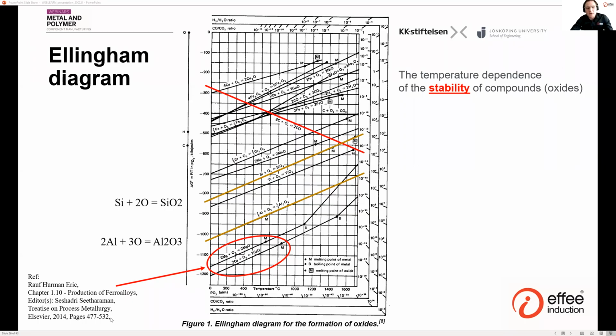This is used very much to reduce other oxides. So if you look on the right of the diagram, where this red carbon dioxide line goes down with increasing temperature, you can see that above, for example, 1400, 1500 degrees, the carbon dioxide line is lower. That is more stable than, for example, chromium oxide or manganese oxide or even silicon oxide. So then you can use carbon to reduce this, for example, chromium oxide. It's very valuable to do that when you make stainless steel, because then you can save a lot of chromium that would otherwise be in the slag and lost.